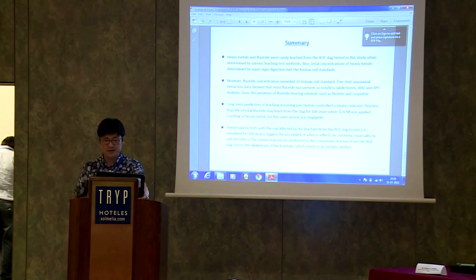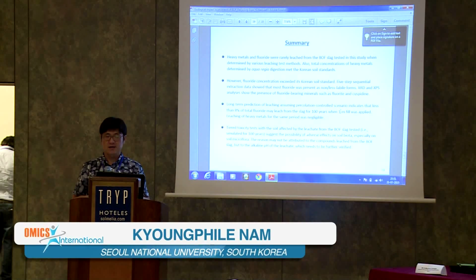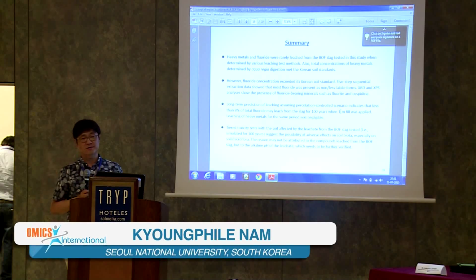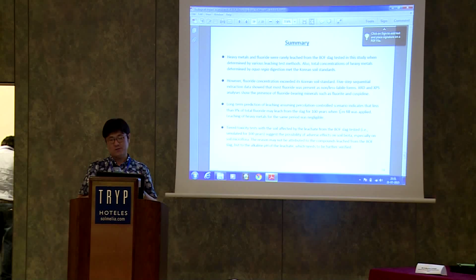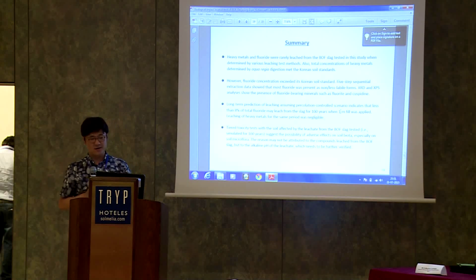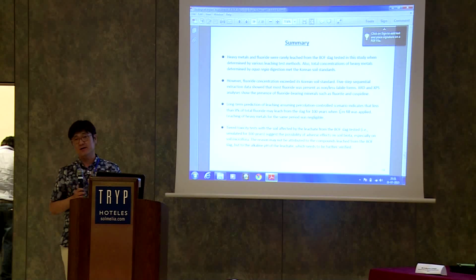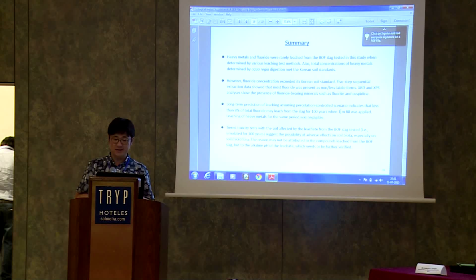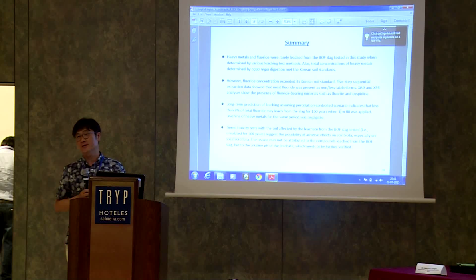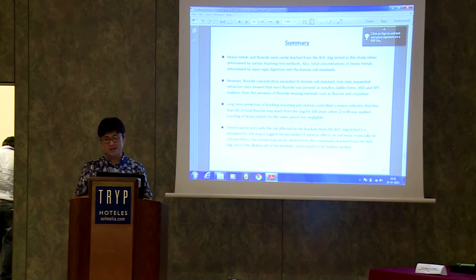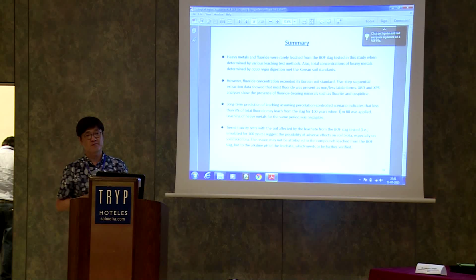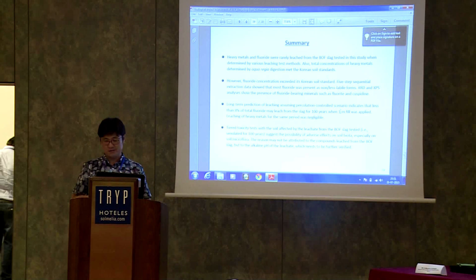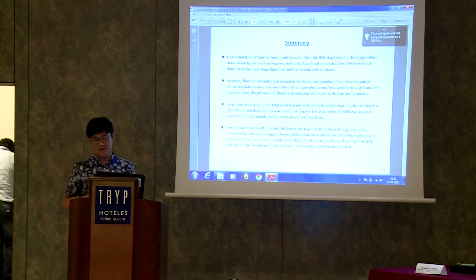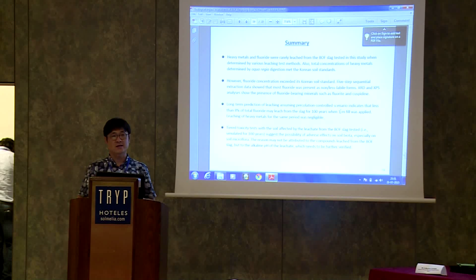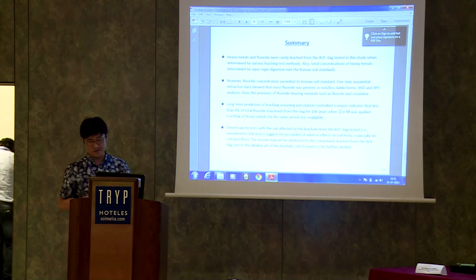And here the toxicity test results show that there seem to be some adverse effects by the slag leachate, but I don't think they are from the heavy metals or fluorine leached from the slag. Instead, it is because of the alkaline pH of the leachate, which is about 12 or 13, but this needs to be further investigated. But from this study, our current conclusion is that the problem is the pH from this slag, not some heavy metals or fluorine compounds. Okay, thank you.